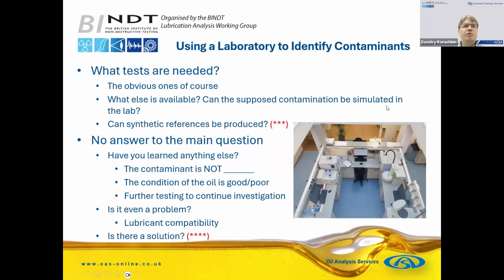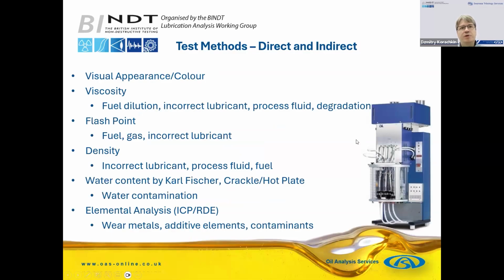So moving on to a few tests. Visual appearance and color may be indicative of contamination. Viscosity can help detect fuel dilution, incorrect lubricants, process fluids, degradation of oil, oxidation, for example, cracking. Flash points for detecting fuel, gas, incorrect lubricants sometimes. Density, different lubricants may have different densities, different process fluids and fuel. Water content can be detected directly by Karl Fischer titration or crackle hot plate, infrared and so on.